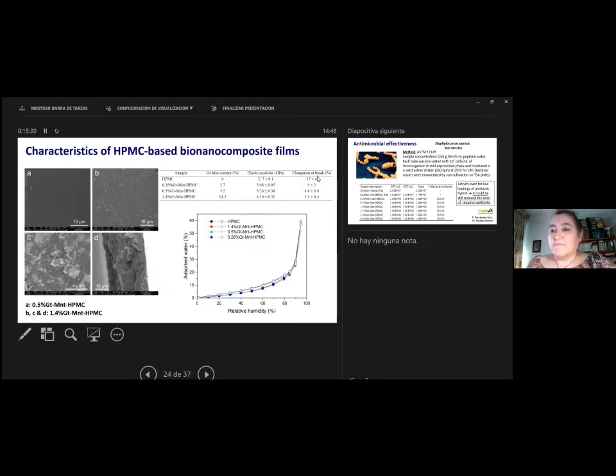Well, it's brittle, because whenever we put inorganic compounds like clays in polymers, sometimes we decrease the elastic properties. And what is important for our application, we observe that the hydrophilic character of the material is practically the same, even when we incorporate a large amount of the hybrid material in the polymer.